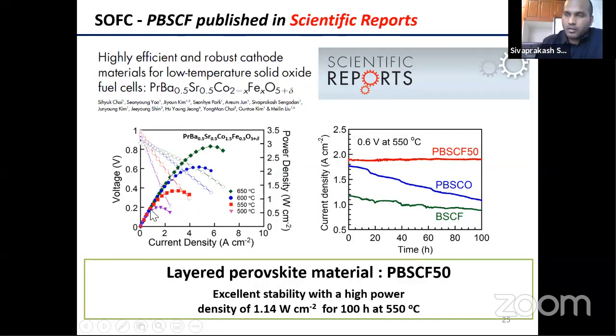Instead of stabilized zirconia, we used stabilized ceria as the electrolyte, nickel as the anode, and praseodymium, barium, strontium, cobalt, iron as the cathode material.